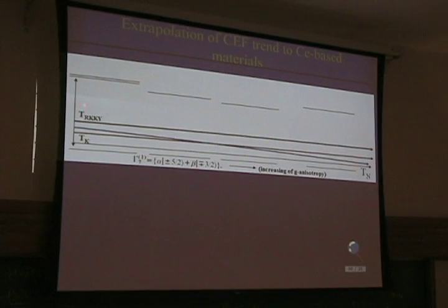So you can go from an antiferromagnet to a system where T_K is larger than T_N, and we compensate that moment. I'm showing a very simple local picture that may have some influence on your Doniach phase diagram.